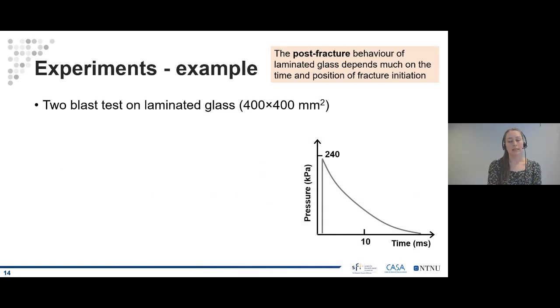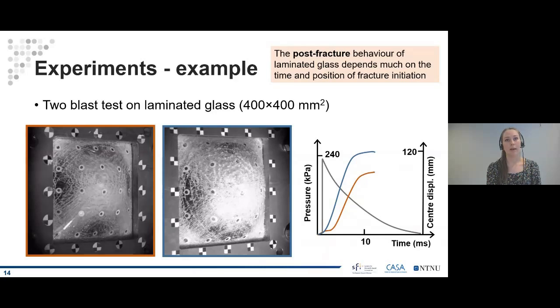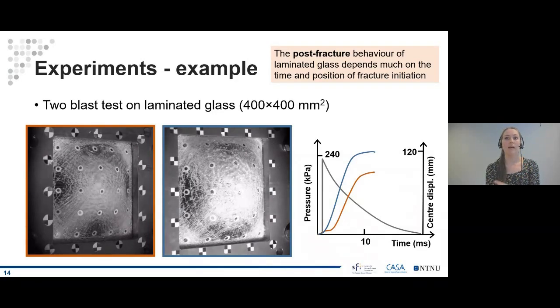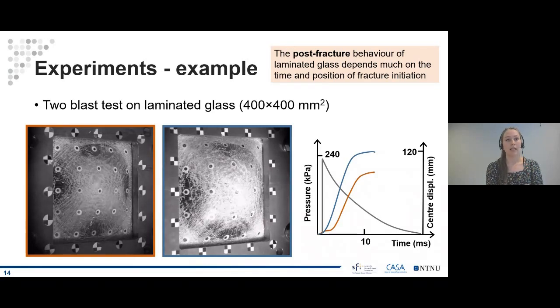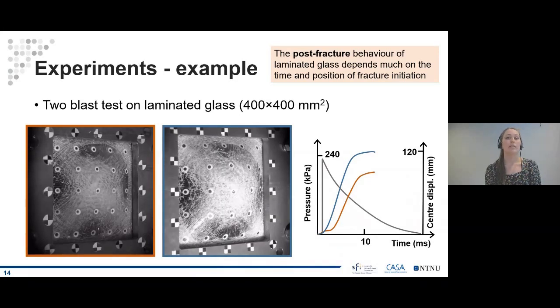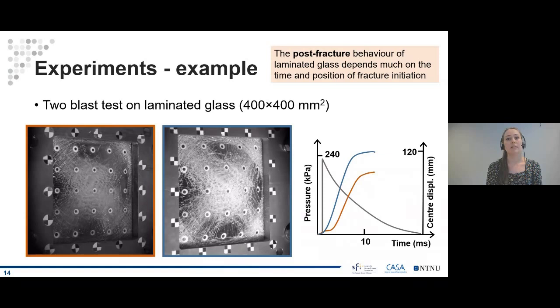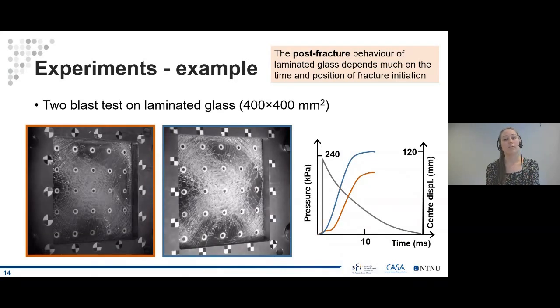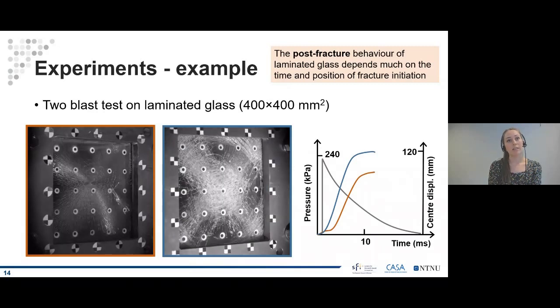I will show you an example of this last conclusion, and I will here present two blast tests on laminated glass, and both of these plates were exposed to exactly the same blast pressure. This is the blast pressure that is shown in this figure to the right. This shows the fracture process of the two different laminated glass plates. Now in the figure to the right, I've included the center displacement of both of the plates. The test that is presented in orange has a 30% less maximum displacement compared to the other one, which is shown in blue. One of the biggest reasons for this difference is the fracture initiation in the glass. In the orange test, fracture initiates later, and it takes longer for the second plate in the laminated glass to fracture. Also, fracture initiation occurs further from the midpoint compared to the other test.